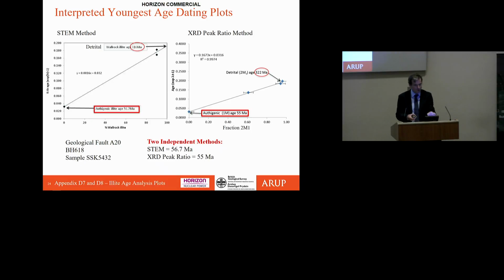And you can see that these older detrital ones, they can go back as 300 million years, and we've got the ages of those. We can find the ones where there's no longer any detrital particles, and they're 90, 95, 100% the authigenic ones that have grown in situ, and we get these ages which are in the order of, the youngest I think was 38 million years, but they're generally 45 to about 75 million years. So that's a fantastic result. And then when we compare the two, we can get fantastically consistent results. You know, this is one example, but it's consistent with many others, that the two different methods would give us 55 million years and 56.7 million years. It's quite, you know, strikingly good results.